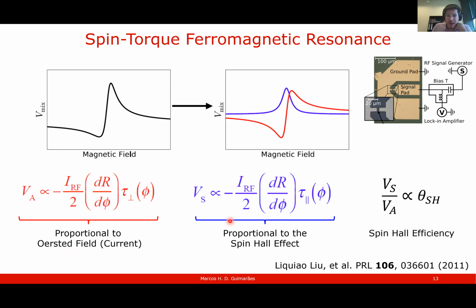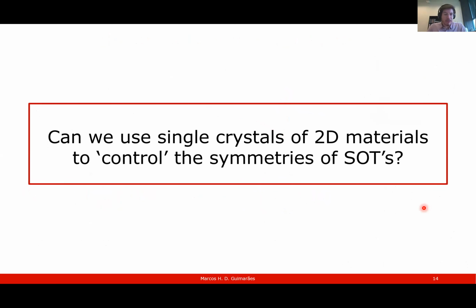Very nicely, if you take the ratio of the amplitudes of these two signals, then you directly get the spin Hall efficiency. So it's a very easy method to directly measure the spin Hall efficiency. But as I told you before, the spin Hall effect and platinum are not very nice systems to get nice spin orbit torques because the symmetry is not quite right and the efficiency is not quite high. So can we use single crystals of 2D materials to control the symmetries of the spin orbit torques? That's the question that I'm going to try to answer here.